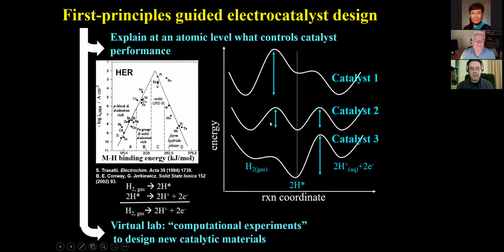And again, our computational chemistry tools then are just letting us map out this curve. How does energy change as we bring hydrogen towards the surface, dissociate it, and then evolve it as protons and electrons when the reaction finishes? And then our goal is to map that back to a design parameter. In this case, it was composition, what we made our catalyst out of. And then we found a descriptor, how strongly does hydrogen bind to the surface.